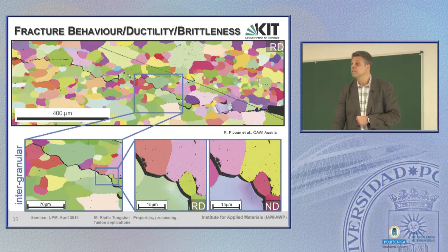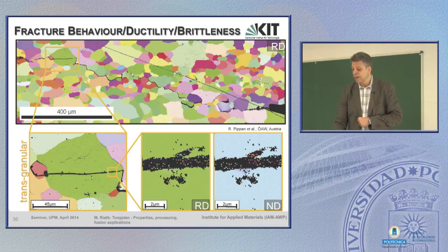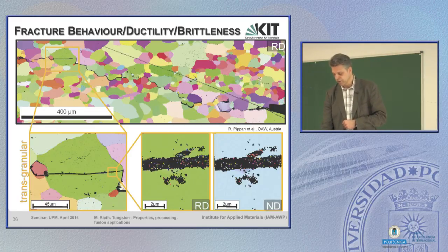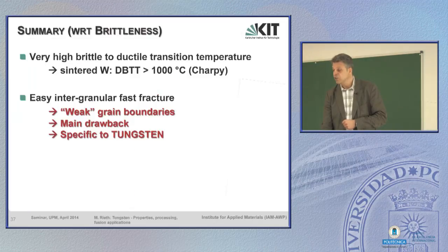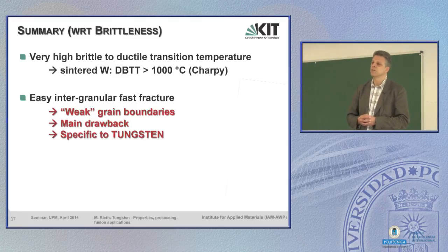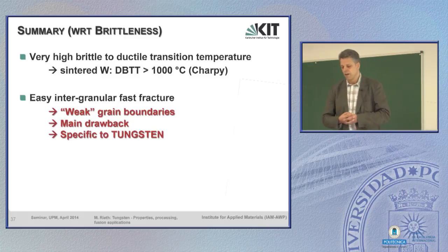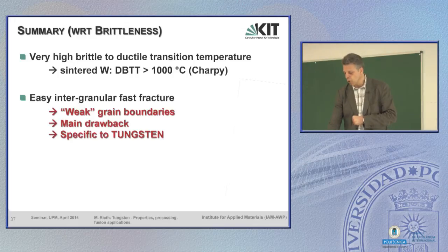And let's summarize with respect to brittleness. We have a very high brittle-to-ductile transition temperature in tungsten, especially in sintered tungsten. DBTT is higher than 1000 C. There is an easy intergranular fast fracture, which means we have weak grain boundaries. That's very specific to tungsten. The grains are not bound together, they are weak. That's the main drawback, and this is rather specific to tungsten. Only molybdenum is more or less comparable to that behavior.